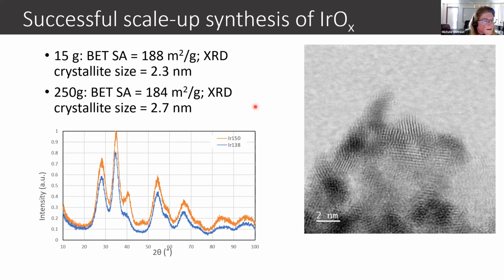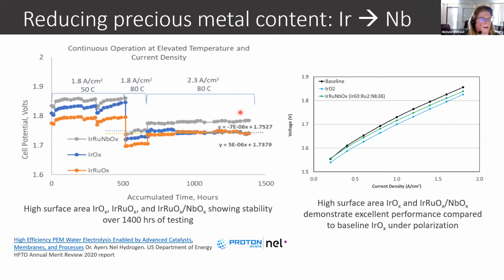Here we've achieved very, very high surface areas of our iridium oxide, which again lends itself to being able to more effectively use this very, very expensive material. And we've also achieved very good crystallite sizes of about 2.5 nanometers in our materials. So why is this important? Well, when we put these into electrolyzers and elevate the temperatures and the different current densities, what we see is that our high surface area iridium oxides are actually showing remarkable stability even over about 1,400 hours of testing.